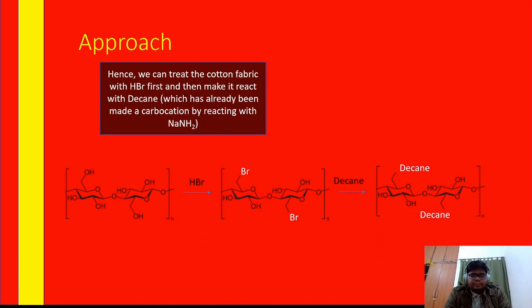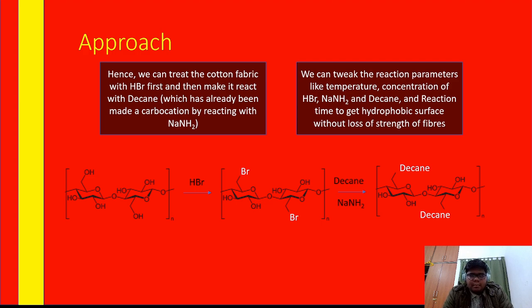So the approach that I propose is we can treat the cotton fabric with HBr first and then make it react with decane, which has already been made a carbocation by reacting with NaNH2. So you have cellulose, it reacts with HBr, the OH is replaced by Br, and then we use a decane carbocation and the Br is replaced by decane such that decane is directly attached to the cellulose fibers. We can tweak the reaction parameters like temperature, concentration of HBr, NaNH2 and decane and reaction time to get hydrophobic surfaces without loss of strength of fibers.